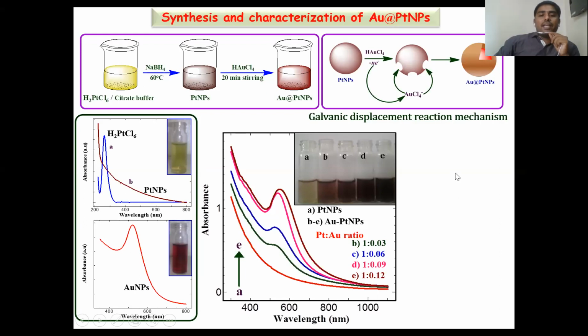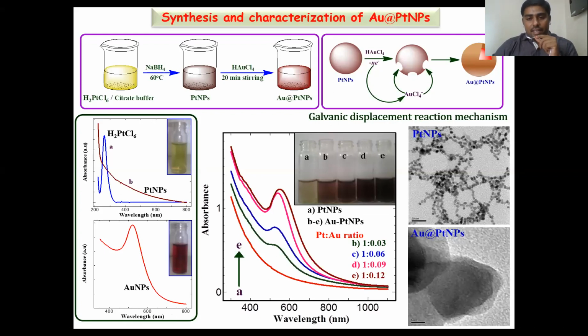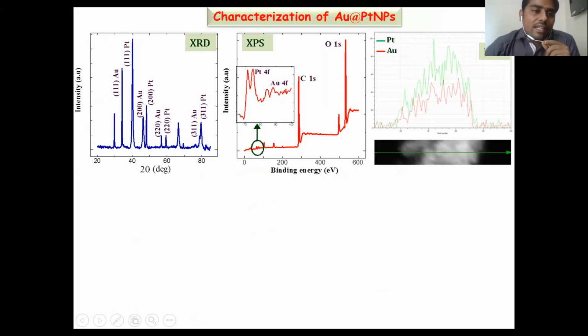Initially the platinum nanoparticles were formed, and then auric acid was added. The platinum nanoparticle acts as an autocatalyst and reduces the auric acid to gold nanoparticles, and the platinum itself is oxidized. The reduced gold nanoparticles were placed inside, and the oxidized platinum covered the gold nanoparticles to form gold platinum bimetallic nanoparticles. This was confirmed by HRTEM images: the platinum nanoparticles were very spherical particles, and after the formation of gold platinum bimetallic nanoparticles, we can see 2 layers of nanoparticles.